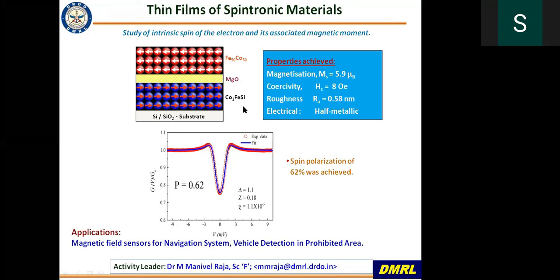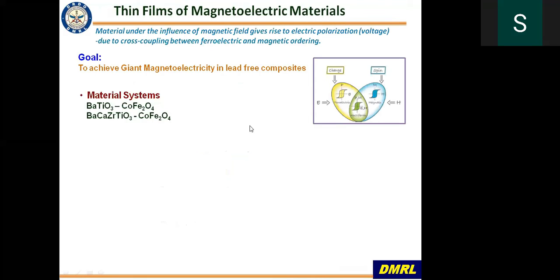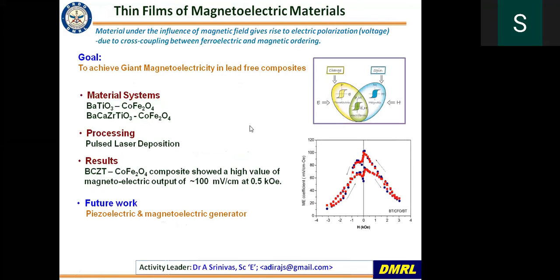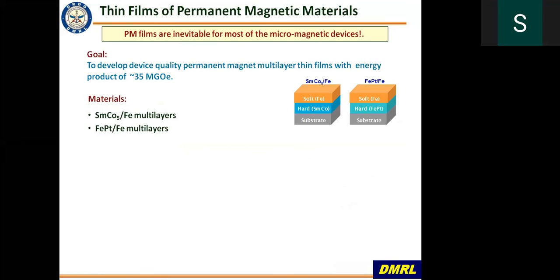We can successfully overcome this challenge, and we have also carried out magnetoelectric based material work where we use a magnetostrictive material and a piezoelectric or ferroelectric material. We have a bilayer of these two materials. When you apply a magnetic field, the magnetostrictive layer produces a strain, and this strain is imparted to the piezoelectric or ferroelectric layer. As a result, a voltage is generated. This is used in electric energy harvesters, piezoelectric magnetic generators, etc. So this is also one of the areas being carried out.